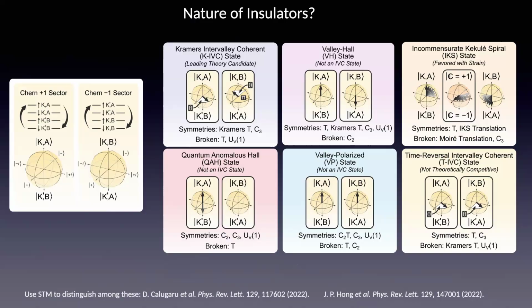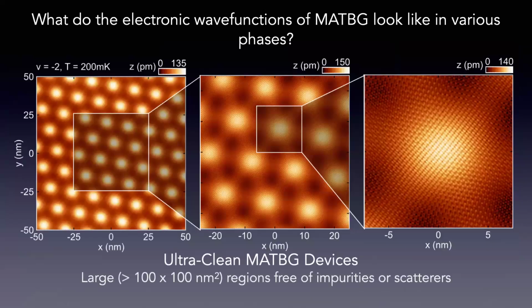Okay, so here is the zoo of states that has been proposed for the insulating state. At the time that we got started, I think this state, KIVC, which has these symmetries and these broken symmetries, was one of the leading candidates for the insulating state. And a highly exotic state with actually loop currents in it was this. That turns out to be not the state. So how do we find that?